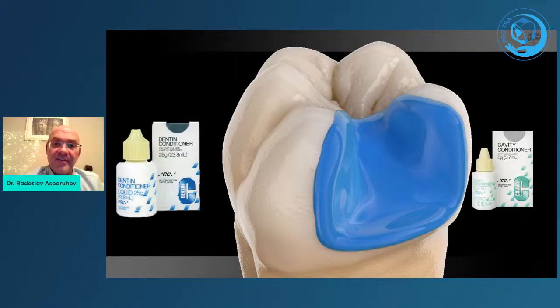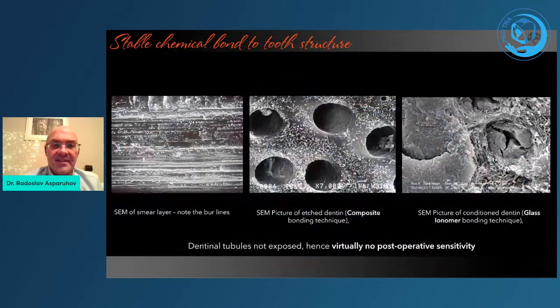But to compare the effects of the conditioner, I would like to show you a SEM picture of etched dentin with orthophosphoric acid. That is the one in the middle. The picture on the left is the smear layer that is left after the preparation with a burr. The one in the middle is etched dentin with orthophosphoric acid. And the picture on the right is the conditioned dentin after being treated with dentin conditioner. So you can see that the dentinal tubules are closed.